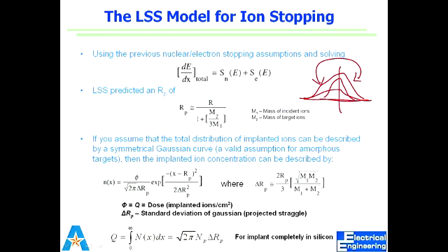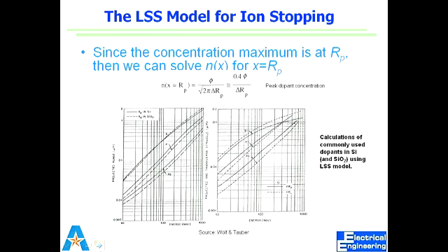There are models where we plot them, that gives us these relations which we can use to get our recipe, right? So when you do your process, you will use these charts to define your energy based on the depth you want, right? If you use an energy to figure out how deep you have your profile, you use these, which are calculated from that relation, right?